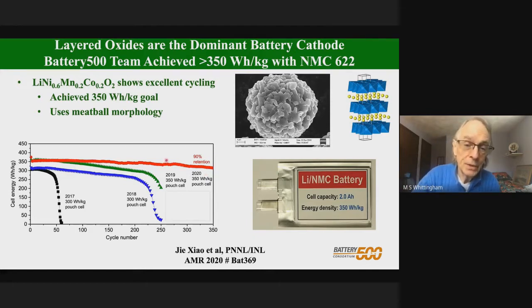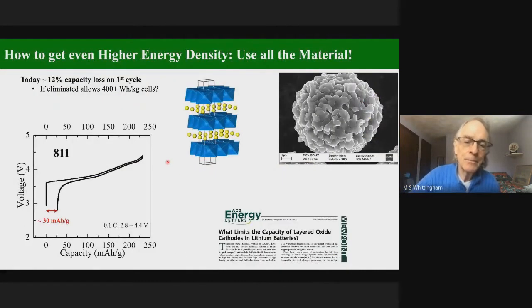What we did to do this, we had to change the electrolyte from the standard ones, and we're now achieving 400 watt hours per kilogram for a few cycles. So we're meeting the goals, getting closer and closer to 500. We're using pure lithium metal in here, so this may cause some safety issues, but we're handling that. But one of the things we have to do is use all the lithium metal.